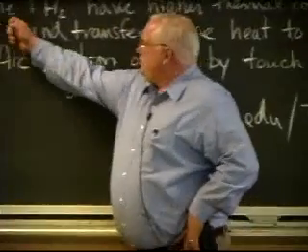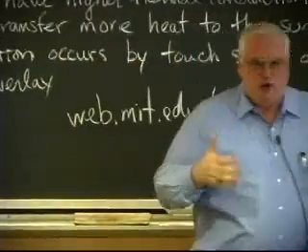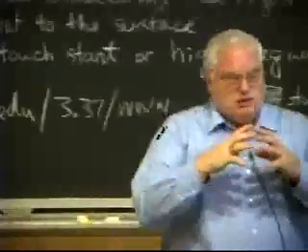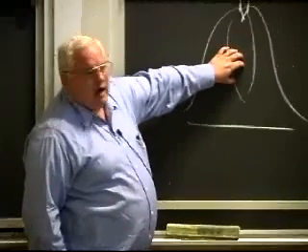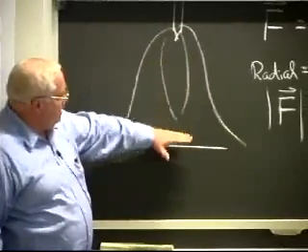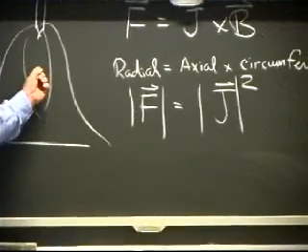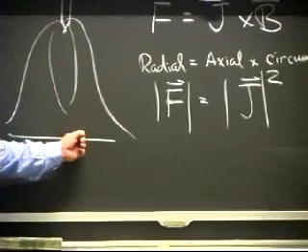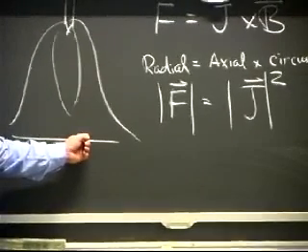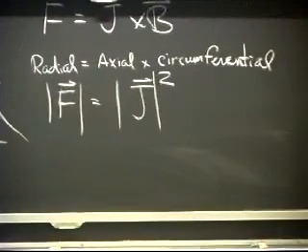Yesterday we talked about different shielding gases. We had talked about helium the day before, but I talked about diatomic hydrogen and how it has a reactive thermal conductivity. Basically, in the body of the arc, you break down the diatomic hydrogen into monatomic hydrogen, and down here in the boundary layer, it recombines. So you have a heat of dissociation being put into the hydrogen here, and it gives up that heat of dissociation as it recombines, or sometimes called the heat of recombination. And that effectively transfers extra heat to the surface.